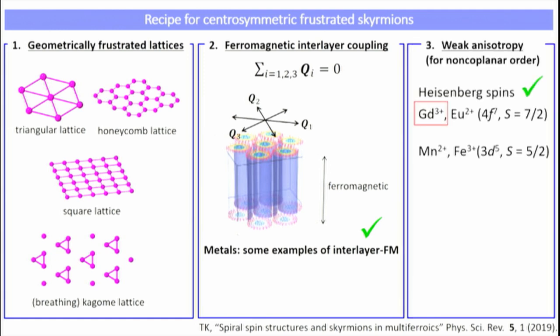But is it necessary to have atomic layers in order to have the Skyrmions, or how thick could your film be before it would? So I'm looking for the Skyrmion state in the bulk sample. In the thin film, it can stabilize the Skyrmion state with a different mechanism, the DM mechanism, because of the inversion symmetry breaking of the thin film. But in the case of the bulk sample with centrosymmetry, there's no DM interaction. The frustration mechanism can be the driving force to stabilize the Skyrmion.